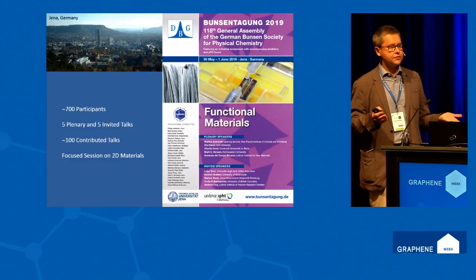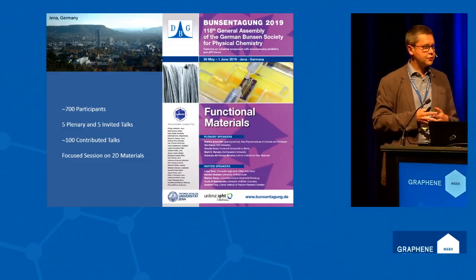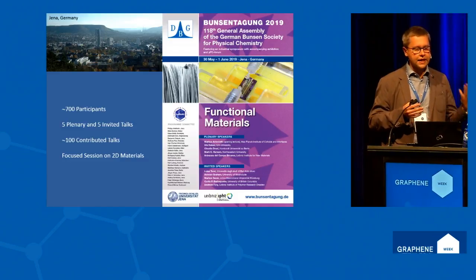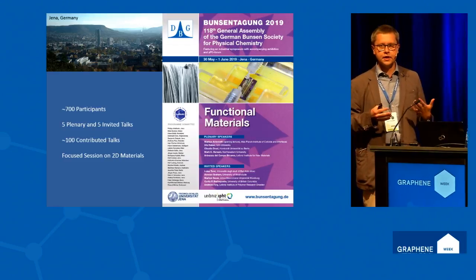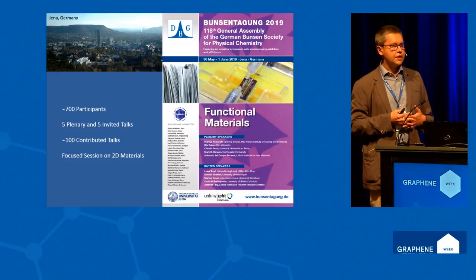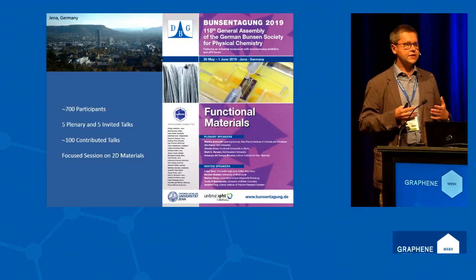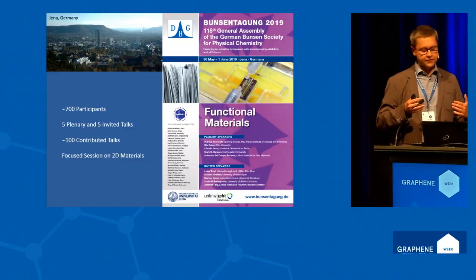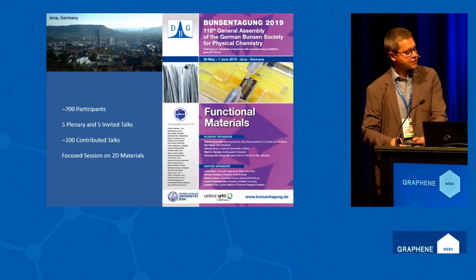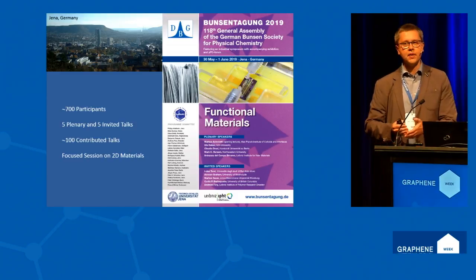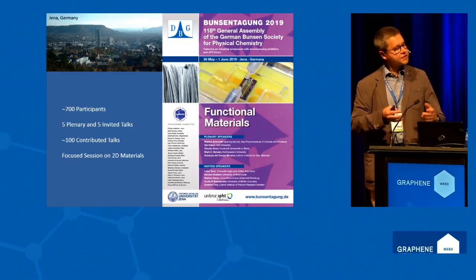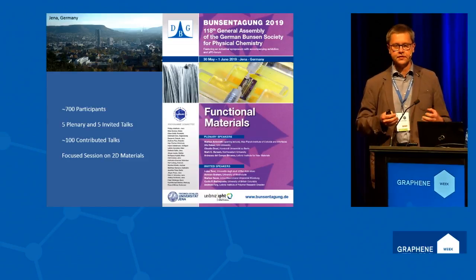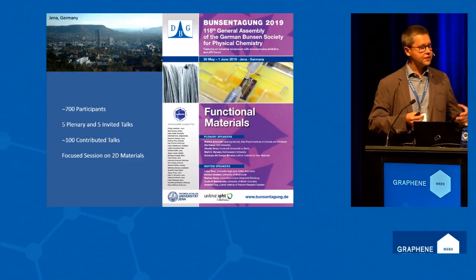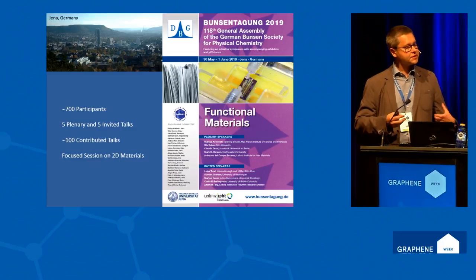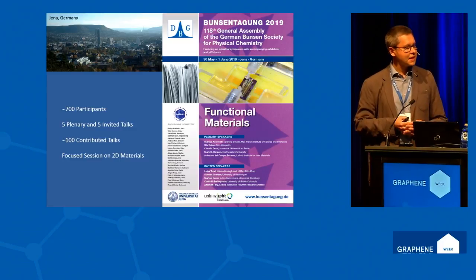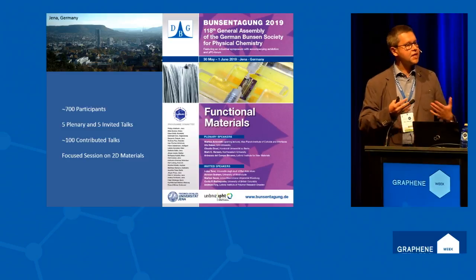We actually transfer graphene, we transfer molybdenum disulfide, tungsten disulfide, these materials with which we have most of the experience. I cannot say that the handling of these materials is much more delicate if you transfer them from one solid substrate to another solid substrate. They are much more delicate maybe if you would like to make freestanding structures, completely freestanding. Then it's much easier to work, for example, with these polymer-like materials in comparison to single crystalline material. This is where I see maybe the main difference.